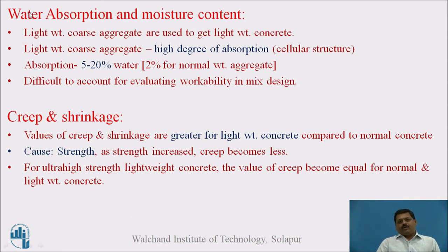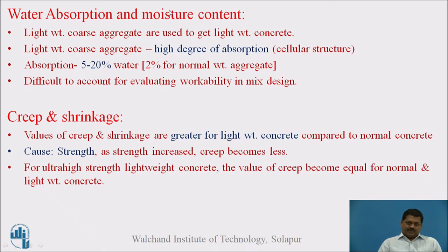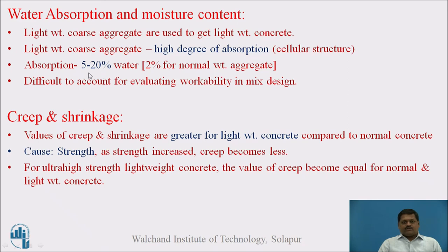Now let us see absorption properties — water absorption and moisture content. Generally, Lightweight Concrete is produced using lightweight coarse aggregates, which have a higher degree of absorption because of their cellular pattern and highly porous microstructure. These aggregates absorb more water, with absorption between 5 to 20 percent, which is really high compared to normal weight aggregates at about 2 percent. This makes evaluating workability in mix design very difficult, as the water intended for hydration may be absorbed, causing workability issues.